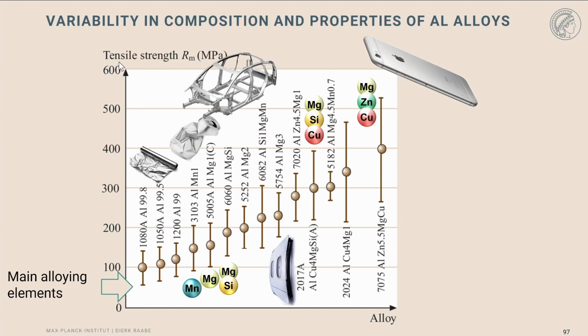We plot here the tensile strength of aluminum alloy as a function of the overall alloying content. And you see here the main aluminum alloy classes like the 1000 alloys, which are relatively pure and used for packaging. We see the manganese containing 3000 series alloys also for packaging. We see the higher strength 5 and 6000 series alloys that you, for instance, encounter in car design. And we see really high strength 7000 alloys that you use for plane components for cars, but also for mobile devices.